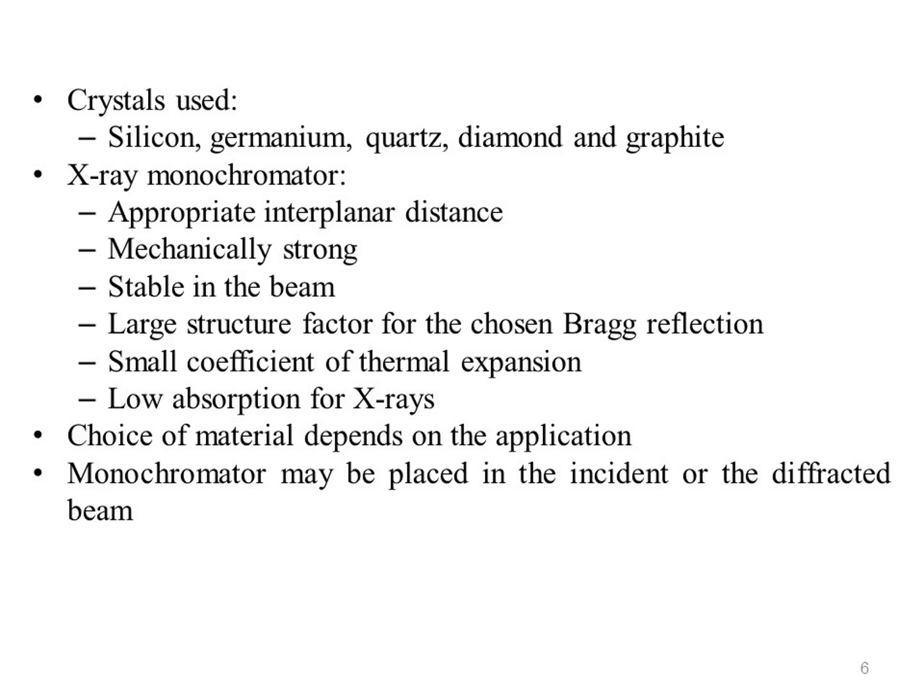The actual choice of material also depends on the application and may take into account the thermal conductivity, degree of crystalline perfection, intrinsic breadth of the Bragg reflection, which is the Darwin width, etc.